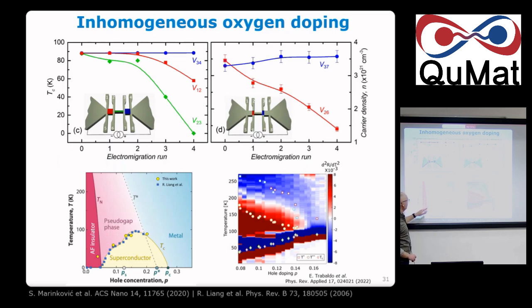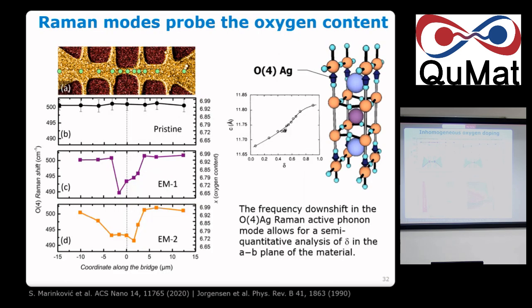And in that way, we go very quickly here. We try to put some points in the phase diagram, and we show indeed that they are not that bad. Of course, we didn't do a very good job. And some other colleagues from Sweden, Chalmers, they did more properly. They apply our technique. They are sample growers. They did very well. So the phase diagram, you can build up with that. And to show that we have oxygen depletion, we did a bit of Raman investigation.